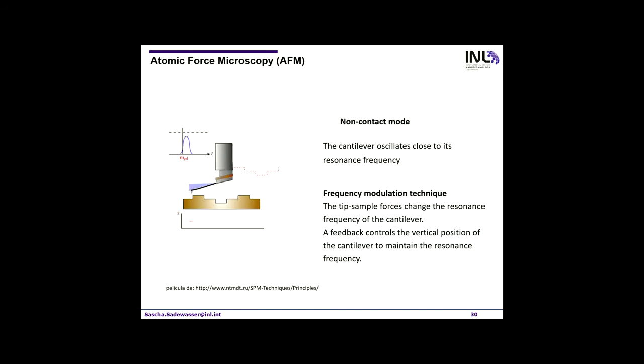And then this is the frequency modulation technique. So here the idea is always to excite in resonance. As soon as your resonance curve shifts, you move your tip, and you normally have a phase lock loop to detect where your resonance maximum is, and then it always excites on the resonance. So here you use a different kind of feedback to adjust your tip height. So always exciting on resonance, and then shifting your Z piezo so that you maintain a certain frequency shift with respect to the free resonance.